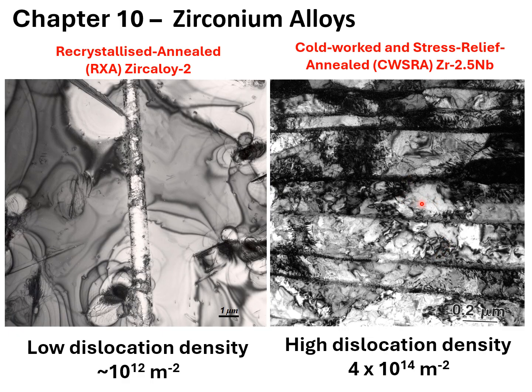And one of the things you should notice is there's all these little black lines in here. If you remember, I talked about line defects. Really, these are dislocations. These little black lines are the dislocations in pressure tubes, and there's a very high density of dislocations in a cold work pressure tube. What this means is that the dislocation density is, in this case, 4 times 10 to the 14 per meter squared of dislocations in the material.